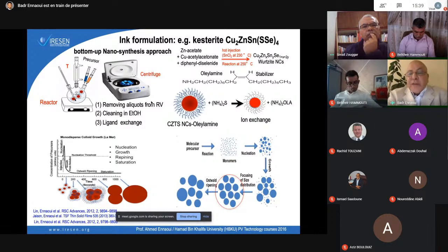The problem, of course, with this additive, in order to avoid the growth of big particles, is that they contain a lot of carbon. And at the end, when you make annealing, the carbon cannot go out as a volatile byproduct, but it can stay in the material, and sometimes it will change your electrical properties in a bad way.